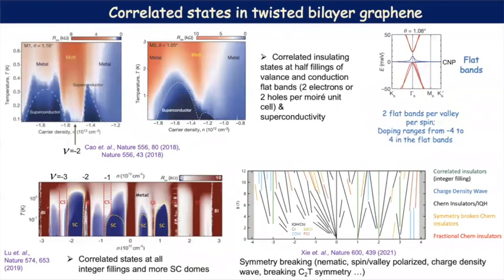To begin talking about correlated states, the story started here in 2018 from Pablo's group, where we saw these correlated insulating states at the half filling of the valence and conduction flat bands and nearby superconducting domes. And I just want to mention one thing. This is the actual carrier density, but I'm going to mainly use this one, which is the carrier density divided by the Moiré unit cell area. So per Moiré unit cell, we have 2 electrons or 2 holes where we have this insulating region.